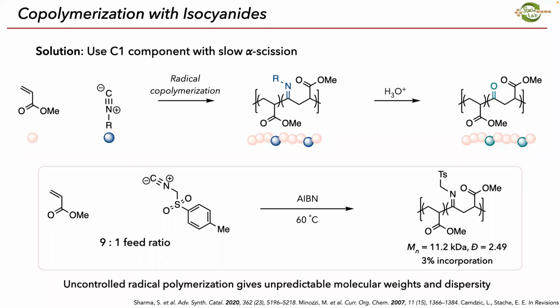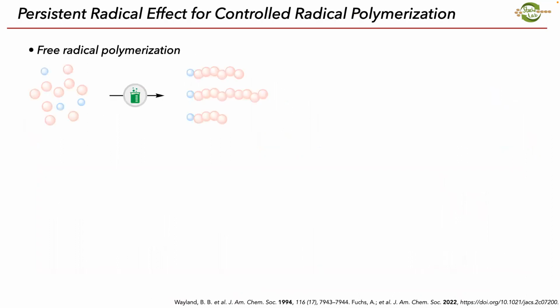So this uncontrolled radical polymerization does not give us predictable molecular weight. And so that means we can't necessarily predict what the properties will be ahead of time. And so we needed to find a different strategy to do this. And so free radical polymerizations, generally we take a thermal initiator like AIBN, which you may have used in lab. And in the presence of monomers, we add some heat, and this will grow polymer chains. And so all of these little pink balls will start adding together and we'll get long polymer chains.